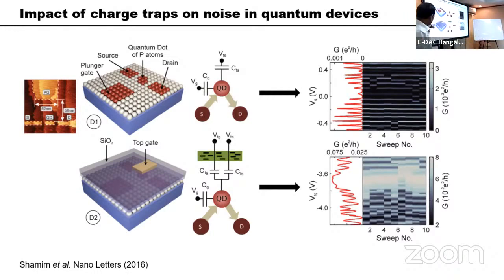However, if all you do is coat a layer of silicon oxide on the surface, silicon oxide is amorphous. Silicon oxide gives you a large number of charge traps, and you can see you completely destabilize the quantum device as you change the gate. They are not stable. They change with time, fluctuate randomly.